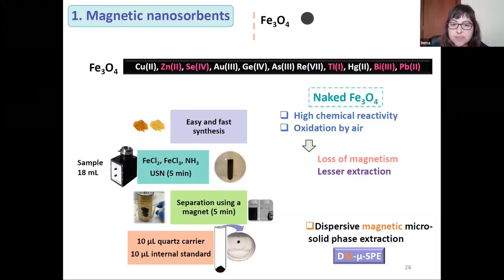Then we have to perform the separation of the nanoparticles enriched with the target analytes from the aqueous solution, using in this case a magnet, an external magnetic field that we can see in this slide. After separation during 5 minutes, it is necessary to wash these nanoparticles because they are in a medium containing a high concentration of ammonia. So we did, I think, 3 washes with ultrapure water, and then we have the nanoparticles. We only deposit on the quartz sample carrier a few microliters of the magnetic nanoparticles, and then we add the internal standard. After aqueous drop evaporation, we perform the analysis by TXRF.